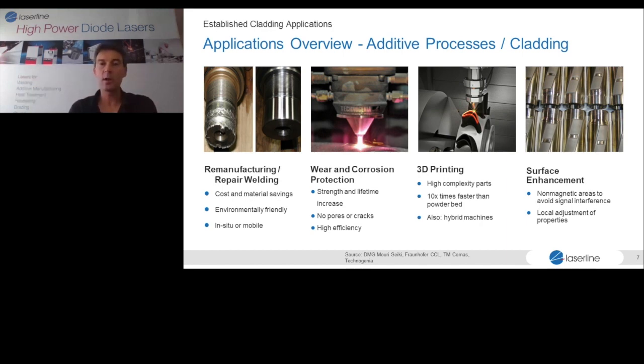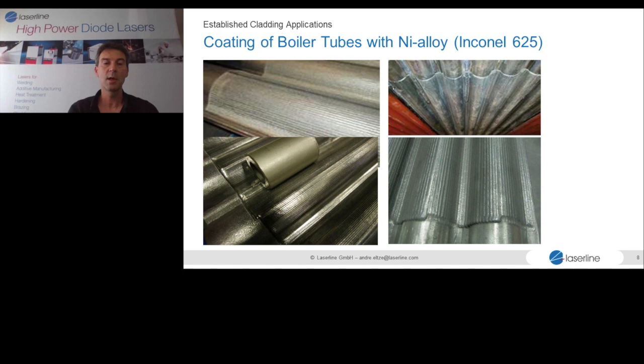For example, when you try to get some signal information through a tube, then you want to have special materials in the surface that avoid interference for a sort of measurement. Typical example, quite recent example, is corrosion protection of boiler tubes, as you can see in the 4 pictures here, just different views of such boiler tubes as examples of applications for corrosion protection.